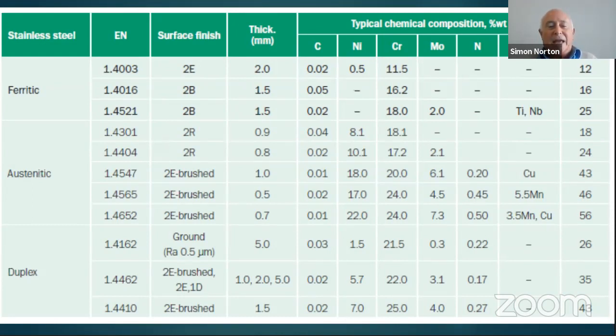Then the surface finish. Now, it is not important to know the various surface finishes that I've shown here. What is important to remember is that surface finish can seriously impact the corrosion resistance of your stainless steel. So how you surface finish your stainless steel and prepare it can have a huge effect on its performance in action in your plant. If you look at the typical chemical composition under Cr and Ni, the chromium and nickel, you'll see that, for instance, the chromium content in the ferritics goes up. When you go to austenitics, 1.4301, that is 304 stainless steel. It's got 8% nickel, 18% chromium. If you look at 1.4404, then of course you've got slightly less chromium, but more nickel, and you've got molybdenum.